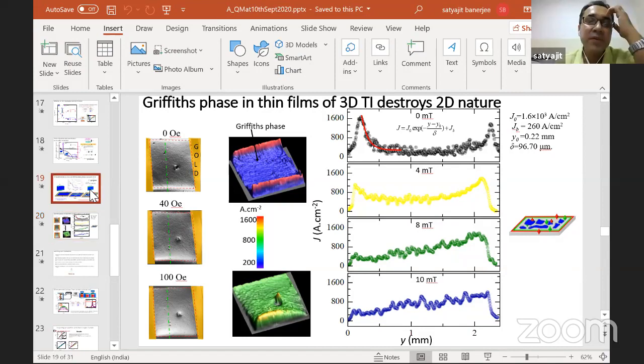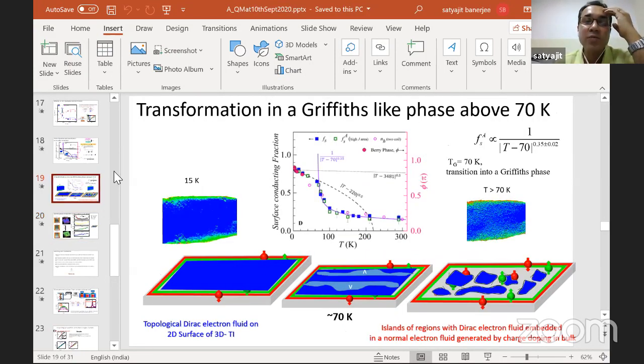No, the Griffiths phase starts away from the edges. What we see is that in the single crystals, for example, this Griffiths phase starts in the center of the regions of the sample, well away from the edges.